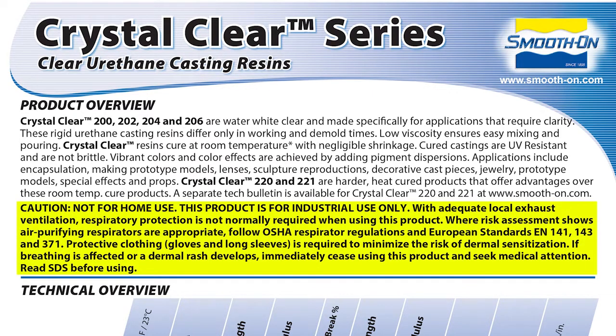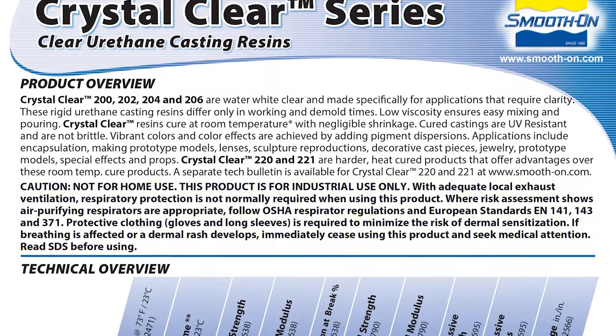Now, because this material is designated an industrial product, we do need to follow the proper handling instructions, which are outlined in the technical bulletin here. Therefore, I will be wearing the proper respirator when handling this material. Again, we're using the 202 today because we are looking for a faster setting material. This has a pot life of 9 minutes, which will work out great for our application of rotationally casting the material. It also has a mix ratio of 100A to 90B by weight, and the Shore hardness for the material is 80D.